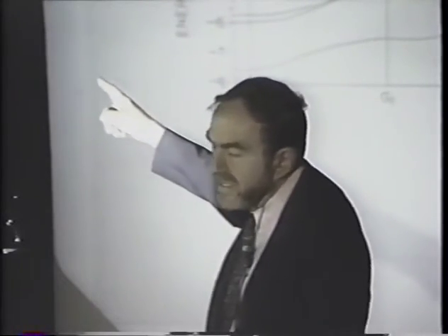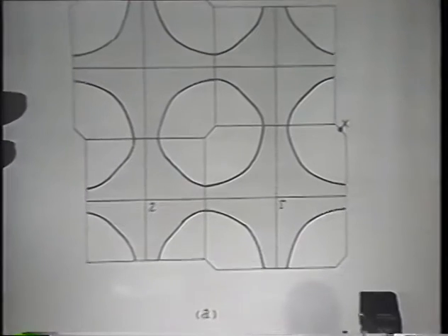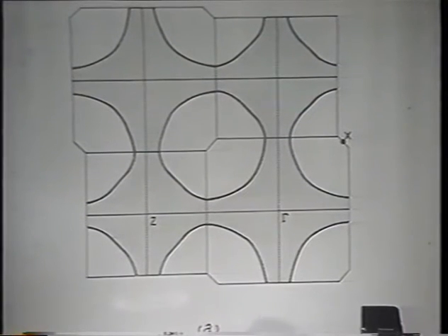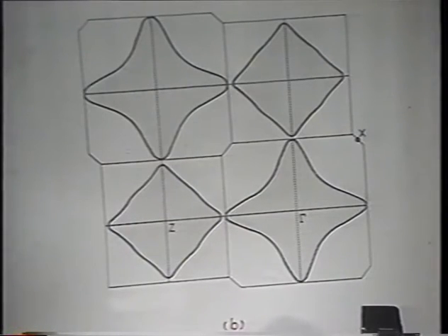In the band structure, there's a very important feature which is shown here. That's the Van Hove singularity. I call it a VHS. That gives rise to an awful lot of physics. It immediately gives rise to a Lifshitz-type transition. This is the Fermi surface for x equal to 0. It's a whole surface around this point. Look quickly, and you'll see that it changes dramatically. It becomes electron surface. This is at the peak, x equal to about 0.16. Then it changes character as you go beyond.